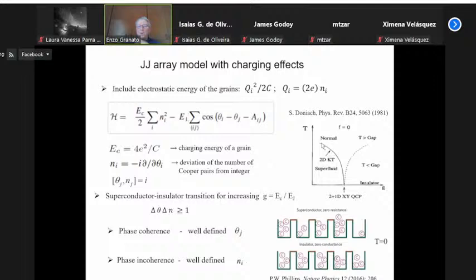For f equal to 0, there is no magnetic field. The critical temperature at zero charging energy would be a Berezinskii-Kosterlitz-Thouless transition. As you increase the charging energy, the critical temperature decreases and eventually goes to 0, and at zero temperature there is a superconductor-insulator transition. If you add a field, then the transition line will change. In particular, as we just mentioned for the honeycomb lattice, there is no transition at zero charging energy. And so the transition line here is, at the moment, unknown.